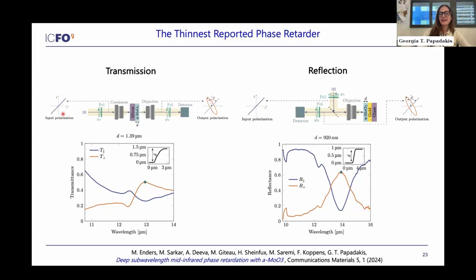You can see here that in the output, we don't have exactly linearly polarized light. We have actually elliptical polarization. And this is simply because to get perfect operation, you need the thickness of the material to be exactly what you calculated. But the problem with these materials is that you exfoliate to get them. So it's very difficult to get the exact thickness right.